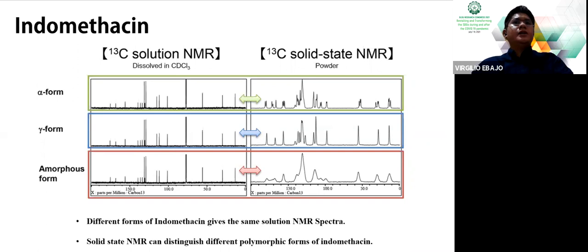However, when the samples are analyzed using solid-state NMR analysis, the two polymorphic forms show different carbon-13 NMR spectra, as shown here. The alpha form has more peaks that are split, while the gamma form has peaks that are wide and are singlets. This shows that solid-state NMR is an effective tool for identifying drug polymorphs, which can be used to ensure that drug products being produced are of the desired polymorphic form.